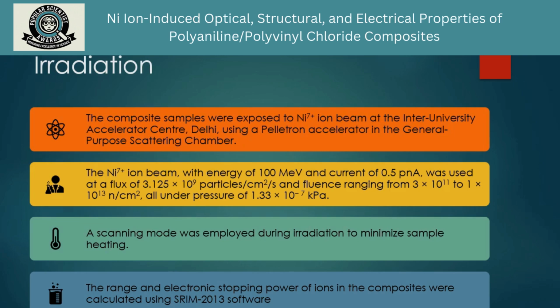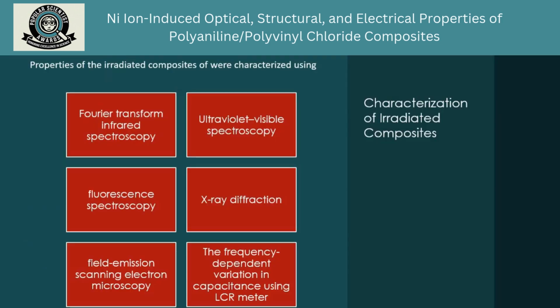And the range and electronic stopping power of the ions in the composites were calculated using SRIM-2013 software and it was obtained to be greater than the thickness of the films, confirming that the ions have not been implanted in the films. Then the irradiated and unirradiated means pristine thin films were characterized for Fourier transform infrared spectroscopy, ultraviolet visible spectroscopy, PL spectroscopy, XRD, FESEM, and LCR meter for electrical properties.